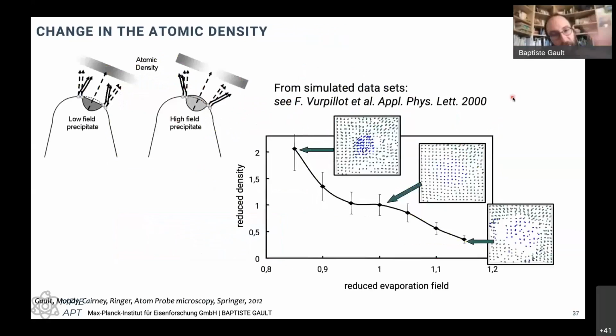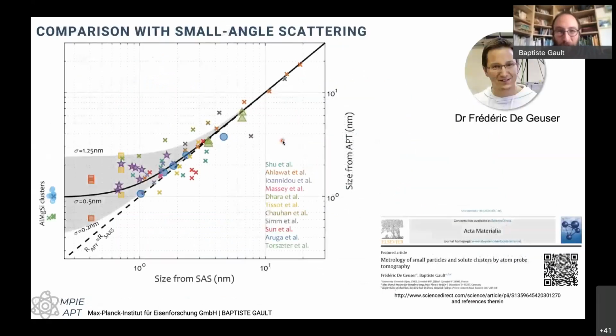So this has been well documented and well studied through finite element method simulations, mostly from about 20 years ago. There's quite a lot of information on this. If you're interested, we can talk about this later. But what we showed last year in comparison between small angle scattering data, either small angle X-ray scattering or neutron scattering, and atom probe, is that the atom probe and small angle scattering sizes seem to match for particles that are above a nanometer, roughly, give or take.